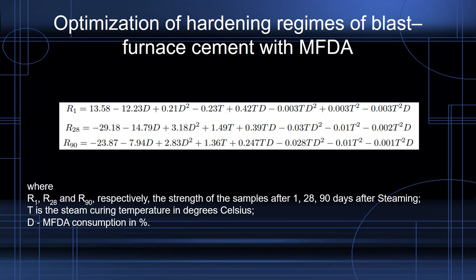The recommended steam curing temperature for ordinary BFC is 90-95 degrees. The introduction of MFDA into the composition of the BFC makes it possible to reduce the steam curing temperature of products by 20-25 degrees. Thus, the introduction of MFDA makes it possible to significantly save energy resources of heat treatment of prefabricated reinforced concrete.